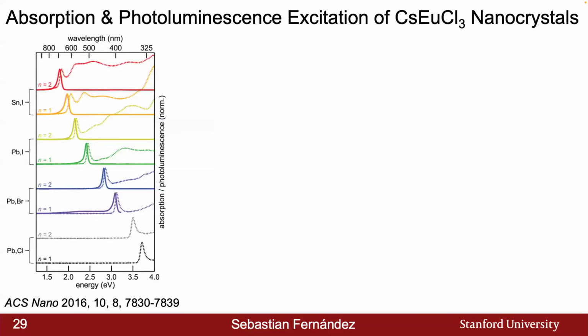So something that we want to mention here is that both for the tin and lead-based system, the absorption and the photoluminescence, as demarcated by the dotted lines and the solid lines, are pretty on top of one another. And this was something that we were not seeing with this Europium-based system, which confused us and suggested that maybe we're not forming what we think we're forming.